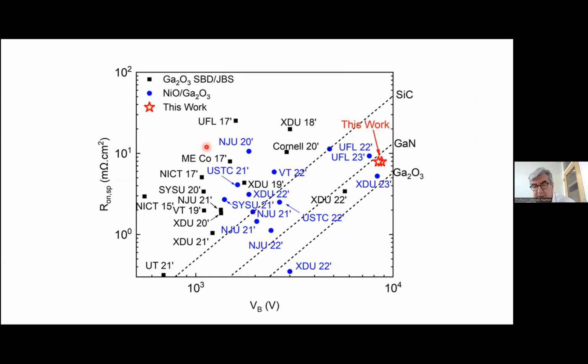The kind of progress has been very encouraging. So if you take that plot of on-resistance versus breakdown voltage for all of the gallium oxide rectifiers reported over the last 5 or 6 years, they started over here a long way from the theoretical performance for silicon carbide or gallium nitride or even gallium oxide. But over that period of 5 or 6 years, you can see everything's moved over here. And now you're getting results that are beyond what gallium nitride could produce and almost close to the theoretical maximum for gallium oxide. So it's a very comforting